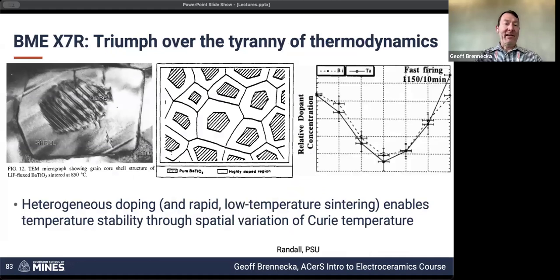And so I promised the image of the chemically heterogeneous core-shell structure. This is a classic image from one of Clyde's papers showing the outside, the shell, of this single grain. This is a single grain of X7R barium titanate. We still call it barium titanate, even though it's got 9 different elements or 12 different elements in it, or something like that. The outside is doped such that at room temperature, where this image was taken, that material is cubic. So the transition temperature between tetragonal and cubic is low enough that this shell region is in its high temperature cubic form, even at room temperature.